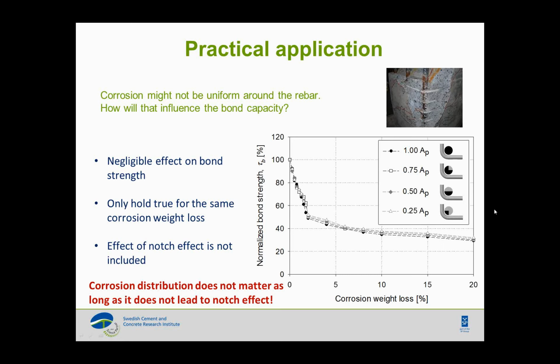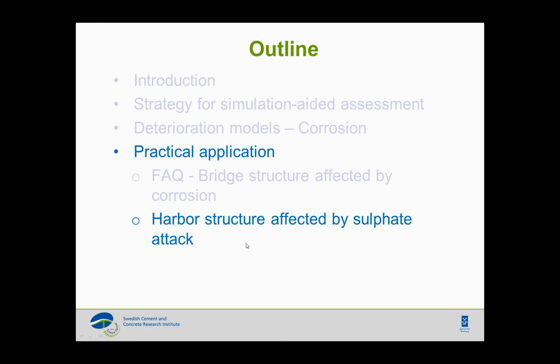I'm not going to describe how we actually implemented the impact of sulphate attack in our simulations, but I can give you a hint that it was very similar to the way that we worked with the corrosion model. In the corrosion model we have this swelling effect at the interface between reinforcement and concrete, and in the case of sulphate attack we have pretty much the same thing. So we impose this expansion within the cement paste, where we have the sulphate attack. So let's begin with this little case study.